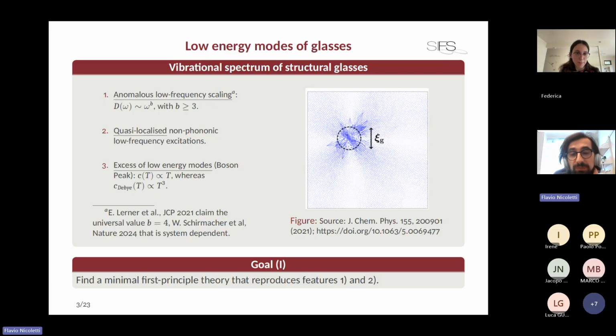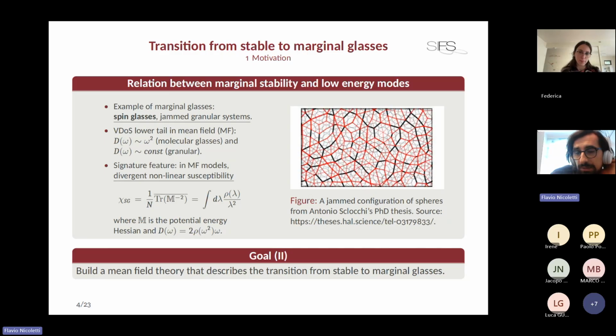So the first goal of our mean field theory should be to see if it's able to reproduce the first two features, that is, a density of states that extends down to 0 frequency and localized soft modes. A second aspect that is important for our theory is that the theory should be able to describe the transition from a stable glass to a marginal glass. So marginal glasses are systems that exhibit extraordinary sensitivity to microscopic perturbations. They feature phenomena known as avalanches, where macroscopic changes in the system configuration can be generated by a very small local perturbation. So an example of a marginal glass is a jammed configuration of spheres.